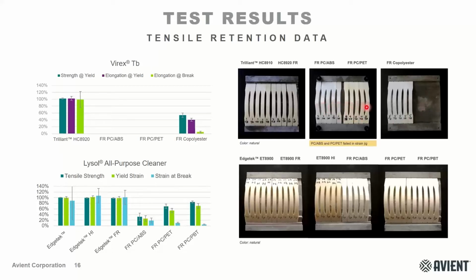The PCABS, FR PCABS, and PCPET actually failed in the strain jig, so you might be able to see the cracking in the bars there. So that's why there's no data here for those. As I said, the FR copolyester didn't exhibit signs of crazing or stress cracking. However, you can see that there's a notable loss in the mechanical properties, whereas the Trilliant material showed almost nearly 100% retention.